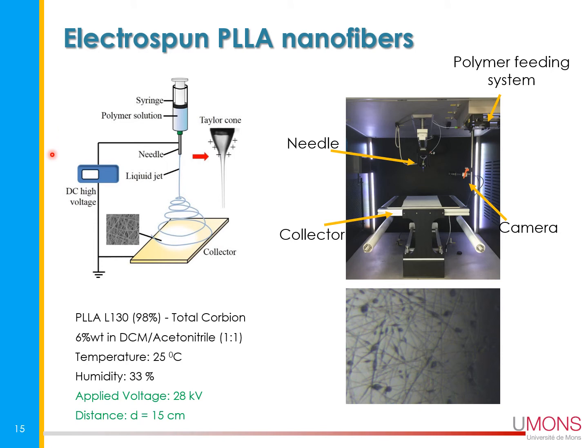So this is the setup used by Kyung, and this setup is actually located at UMET, and this is the way to electrospin the nanofibers. We have a high voltage, a syringe, and the collector, and by changing and adapting all the parameters, it's possible to generate a web of nanofibers as observed here in the optical microscope. The polymer is ejected through a needle which is connected to a DC voltage, and for instance here it was about 28 kilovolts and the distance was about 15 centimeters.